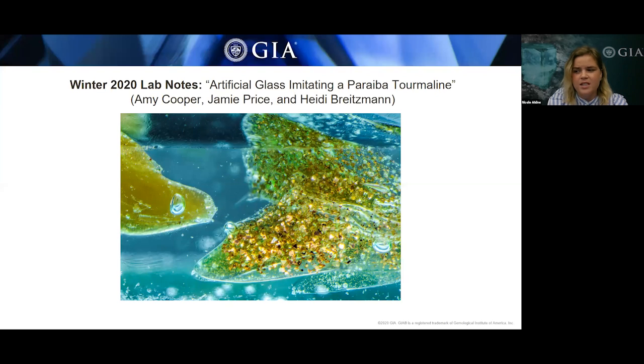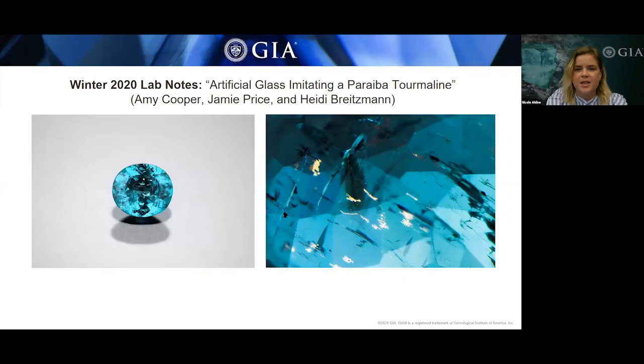Advanced testing was done to confirm that these were man-made glass, as well as the presence of copper from that encapsulated goldstone glass. What was interesting, though, is that during the same time that these manufactured products were being observed, a natural copper-bearing tourmaline from Brazil was being examined in the same lab. So this natural stone has rare dendritic copper inclusions that you can see in the photo on the right, that these two pieces of manufactured glass were trying to mimic.